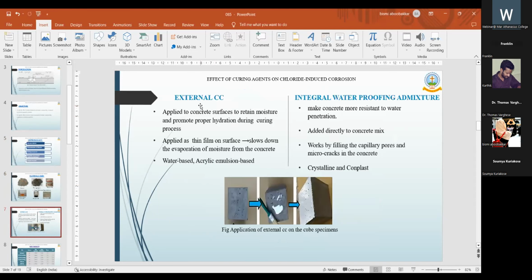External curing compounds are applied to the concrete surface to retain the moisture and promote proper hydration during the curing process. This is applied as a thin film on the concrete surface to slow down the evaporation of moisture from the concrete, as shown in the figure. In this study, mainly two types of external curing compounds are used, that is water-based and acrylic emulsion based.